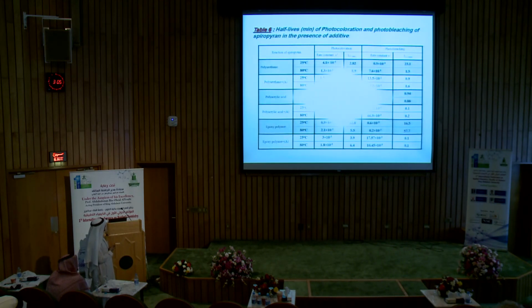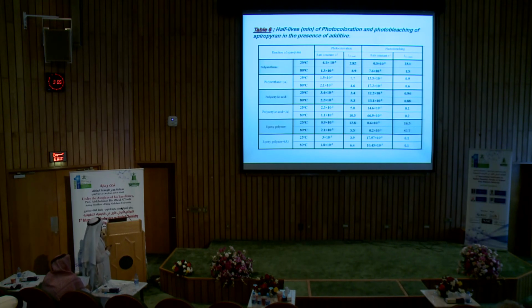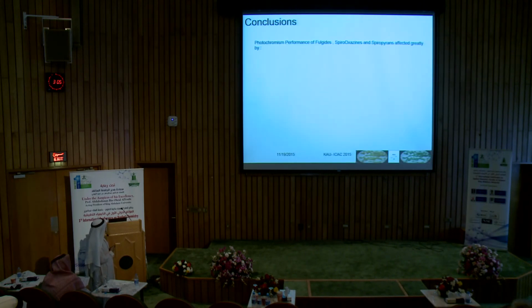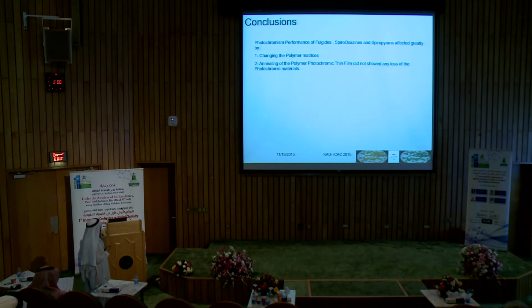And this is the table for the rate constants. Conclusion: the photochromism performance of fulgide, spiroxazine, and spiropyran is affected greatly by changing the polymer matrices. Annealing of the polymer photochromic thin films did not show any loss of the photochromic material. Improvements of the photochromic performance were observed upon annealing.